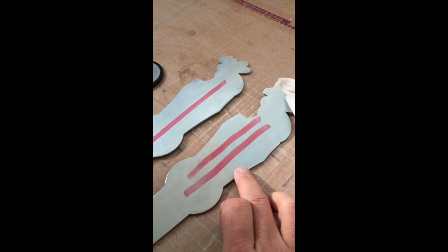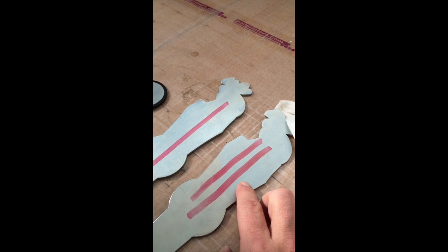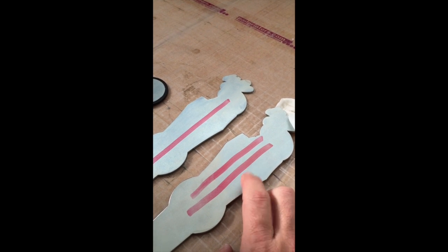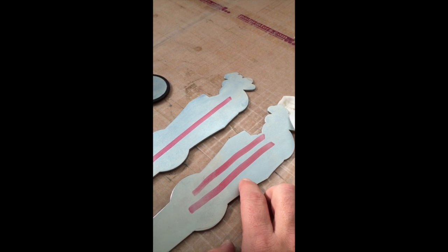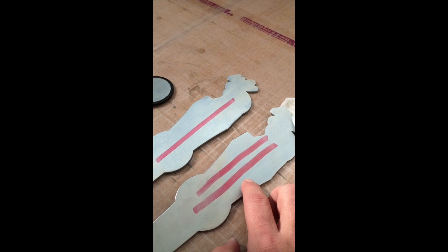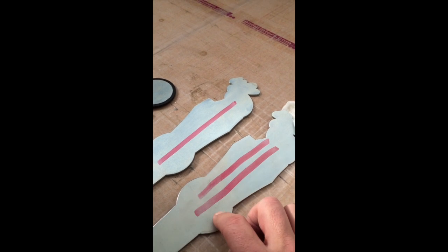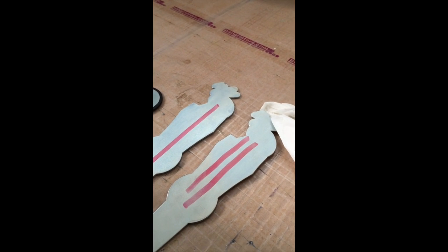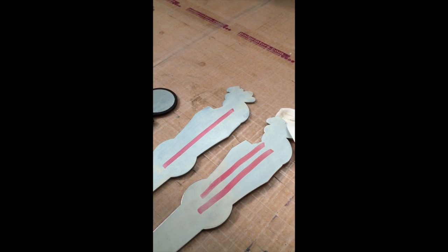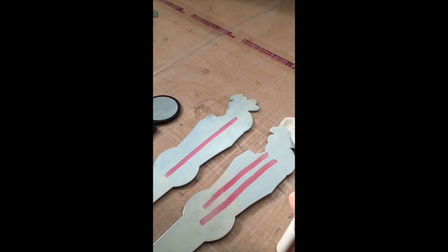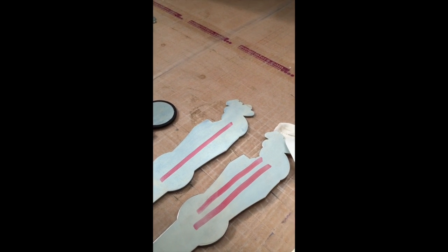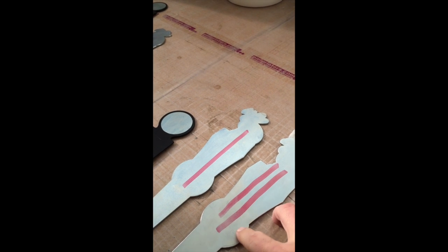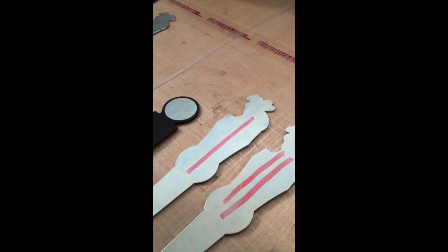It means that there's an enormous amount of contamination there, and you've got some sort of slickness there that the dyne pen is picking up and saying this is going to be much better for the ink to adhere to on that surface than this. Not quite the same as polypropylene, where you have to surface treat it in order to get the tension to change, but what this is showing is that the contamination is oily or slick.